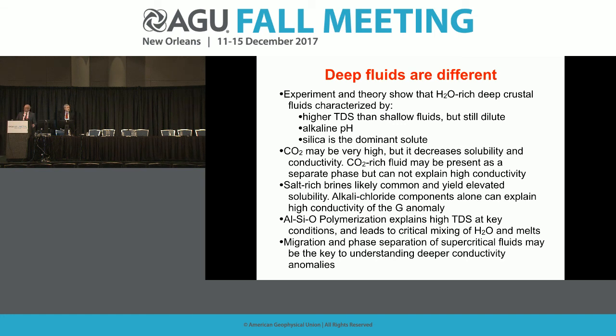But the other thing that matters, and this can be shown just with phase diagrams and so on, is the pH. At elevated pH, you get an additional kick in aluminum solubility from the anion species, the aluminate. On top of that, a number of people who work in environmental geochemistry have shown that very refractory compounds form these very large polymerized structures even at ambient conditions, at extremes in pH, especially in alkaline conditions.